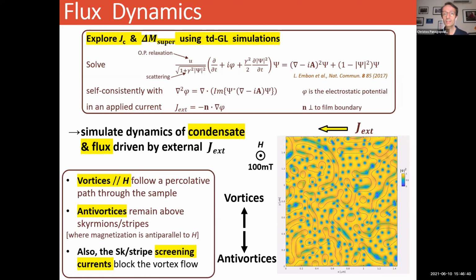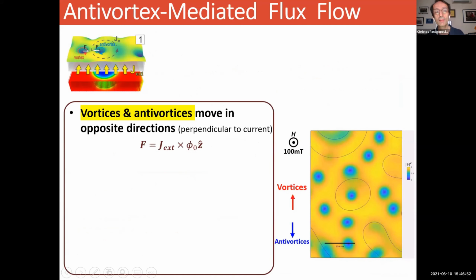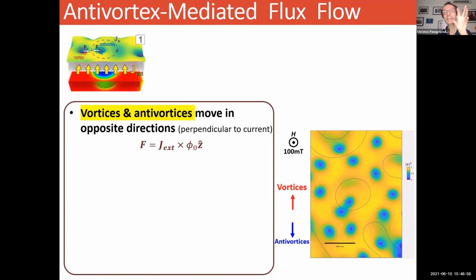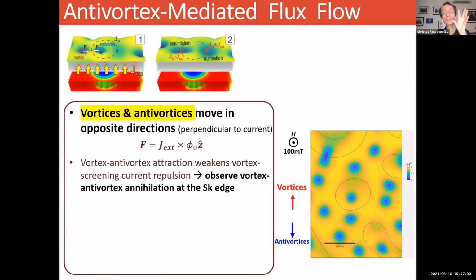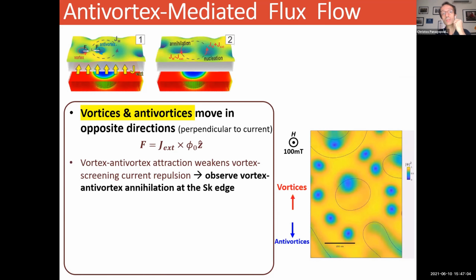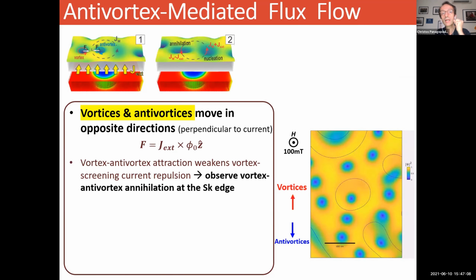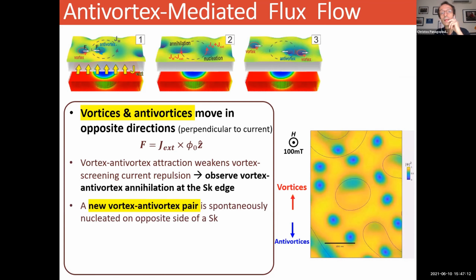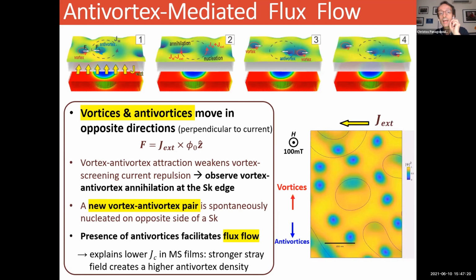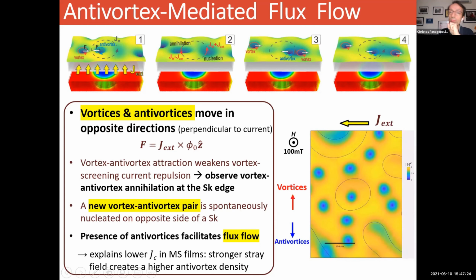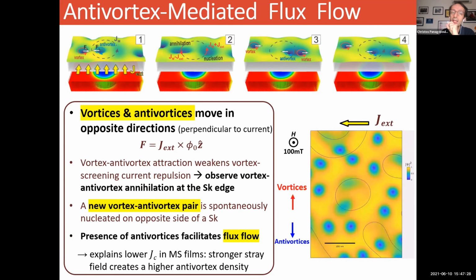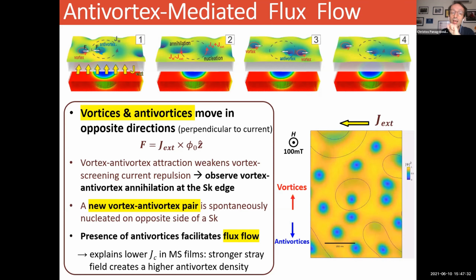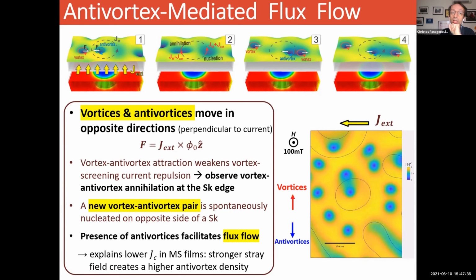So you can see that there is a direct correlation and effect of the skyrmion presence above the superconducting vortices and antivortices. In fact, you can look at this in some more detail, and what you find is that vortices and antivortices in your superconductor move in opposite directions. And the vortex-antivortex attraction weakens the vortex screening current repulsion. Therefore, you observe vortex-antivortex annihilation at the skyrmion edge. Also, you have new vortex-antivortex pairs being spontaneously nucleated on opposite sides of a skyrmion, and the presence of antivortices facilitates flux flow inside your superconductor. And this explains why there is a lower critical current density in MS films. That is because there is a stronger stray field creating a higher antivortex density.